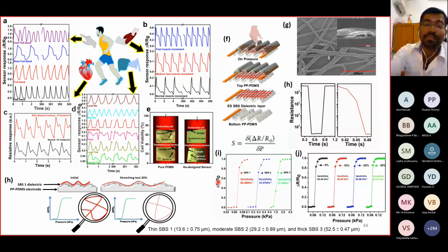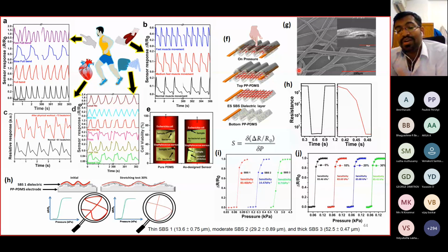Now we are able to see something like a strain-insensitive pressure sensor, because in this case we are forming strain-insensitive electrodes, which maintain their conductivity even under strained conditions. So it can be helpful for a strain-insensitive pressure sensor, because our body is going to move every time, which is dynamic. So it will experience a lot of strain on your wearable devices. Even under that kind of condition, if you monitor your pressure, it is good, right? So we are able to do this kind of experiment, and we harvested very good outputs. Here we can see the resistance value.